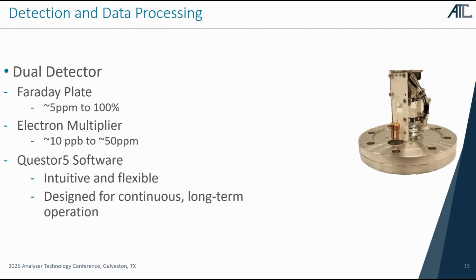After the mass filter, everything goes to a detector and data processing. So for a dual detector, we need to identify both the large bulk air components as well as the trace chemicals that we're looking for. So we use a dual detector, which is going to include a Faraday plate. Faraday plates are usually good for single low double-digit ppm values the whole way up to 100%.